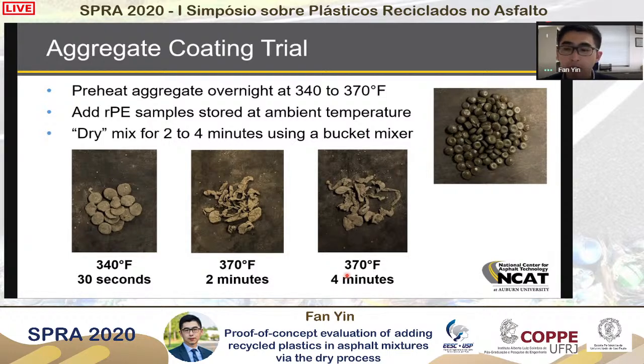So the whole idea I want to show with this picture is, as we can see here, for all these 3 mixing conditions that we tried in the lab, the plastics were deformed because of the shear action applied to those plastics by the aggregate in the bucket mixer. But none of those mixing conditions was able to completely dissolve or melt the plastic so that it can provide the coating of the aggregate. So we were really not able to duplicate the aggregate coating experience that's reported by the researchers in India.